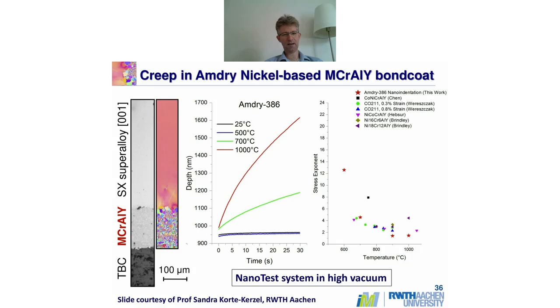And what we can see here is that it's a very, very creep resistant material. So at 500 degrees, it creeps actually in this case even less than at room temperature. So it's really remarkable. But 700 is about its operating limit, and by 1000 you can see there's a transition to a much higher creeping behavior.